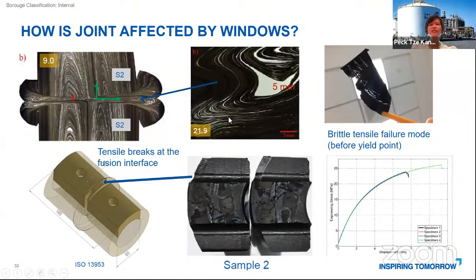So actually, how do this white and black area look? If we take a shaving from the pipe ends, this is how they look. We can even see through it. So this is definitely a very bad UV protection, as well as interference to the jointing. When we do similar tensile tests across the weld, we find that the failure point is at the weld, and it's a very clean cut surface at the failure interface. So this is actually showing that the weld is being compromised. The tensile test also failed in a very brittle way.